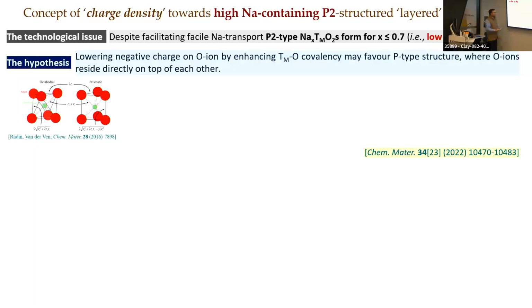What I can see here is that for the octahedral coordination, my oxygen ions are not directly one on top of the other. They are slightly slanted. The center lies a bit away from the center of the bottom one. Whereas for the prismatic coordination, they lie directly one on top of the other. That's the geometry of the coordination.